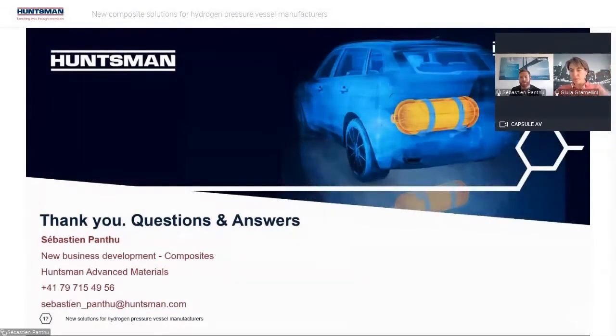Another question. What range of elongation at break do you recommend for the epoxy resin systems for this application? So yes, the higher the better. The thing is, in general, we need to balance all the properties. Especially having thermal resistance means you somehow increase the stiffness, and if you increase the stiffness, you reduce the elongation at break. So it's always playing with the balance, but generally we manage to have a tensile elongation at break on each resin which is above 6.5%.